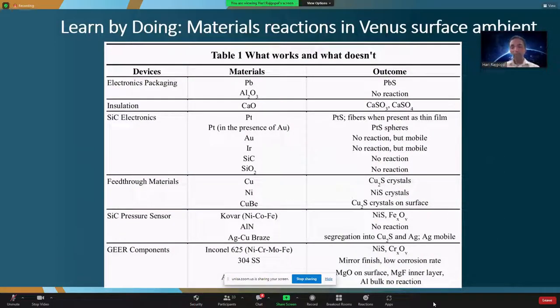And so we have published a paper which says, we learn by doing. We have exposed various materials to the Venus surface ambient, and we have published a list of materials that work and do not work. Obviously, silicon carbide is virtually inert to almost anything. You can only melt silicon carbide with potassium hydroxide at 550 C. Highly basic molten KOH is the only thing that will destroy silicon carbide. And surprisingly, 304 stainless steel is perfectly fine for the Venus environment. Alumina or sapphire is also perfectly fine, no reaction.